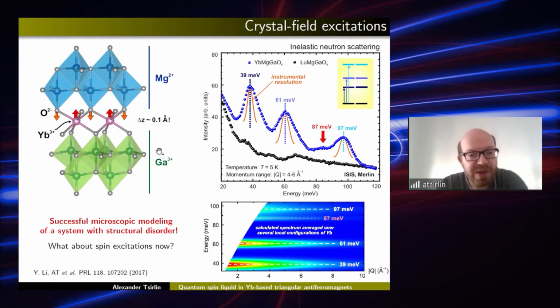And it seems to be important because if I imagine that I have more magnesium on one side of the layer and more gallium on the other side of the layer, then I create some clear charge misbalance so that there is less positive charge on the top and more positive charge on the bottom. And then I can imagine that the ytterbium will move towards the less positive charge, and oxygen will move towards the more positive charge. So this will cause the deformation of my magnetic layer. And these deformations are actually quite significant. About 0.1 angstrom are the typical displacement here. And when you include this, then you can reproduce the experimental crystal field excitations quite well.